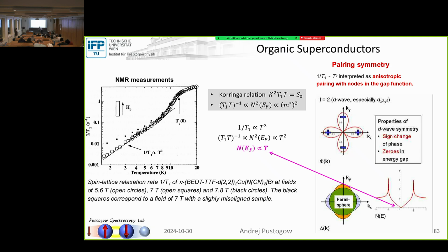If we have the gap as a function of momentum, or the angle phi, then here at 0 degree, here at 45 degree, and here 90 degree, the gap is large at 0 degree, then it goes to 0, and then it becomes large at 90 degree again. And because we have no gap here, this means that here we have metallic electrons.